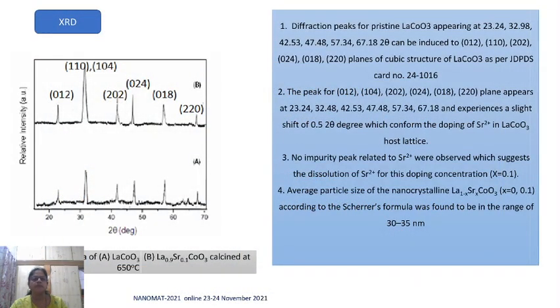XRD. The diffraction pattern of LaCoO3 is as shown in figure A. As you can see, the peaks are appearing at 23.24, 32.98, 42.53, 47.48, 57.34 and 67.18, and these are indexed to 012, 110, 104, 202, 024, 018, 220, as you can see in the figure, according to the cubic planes of the structure as per the JCPDS data.